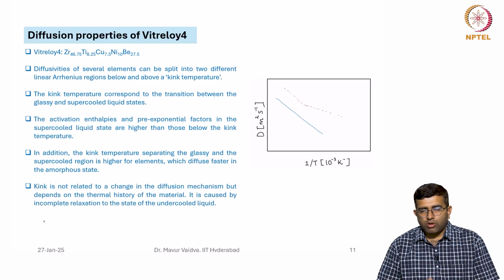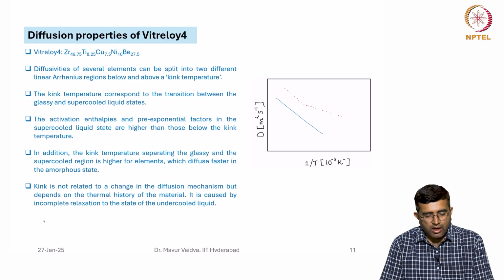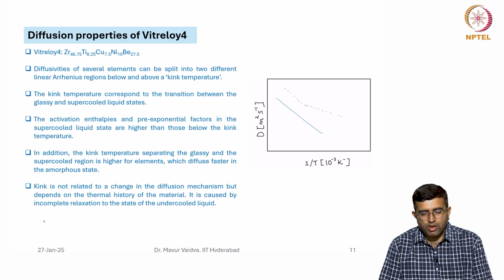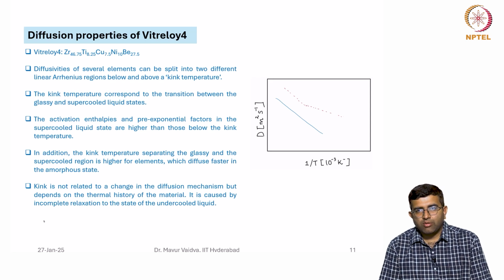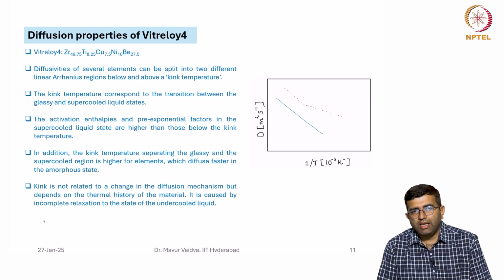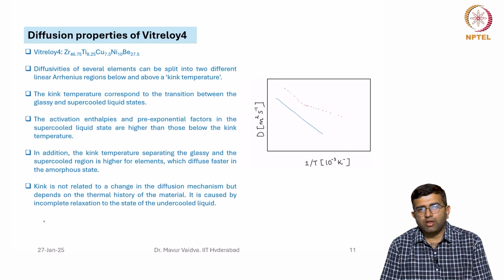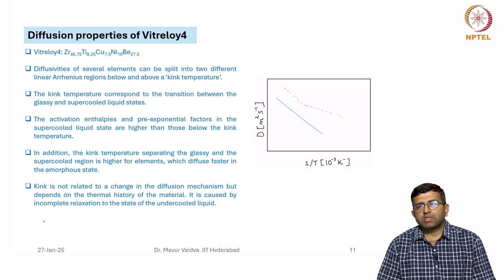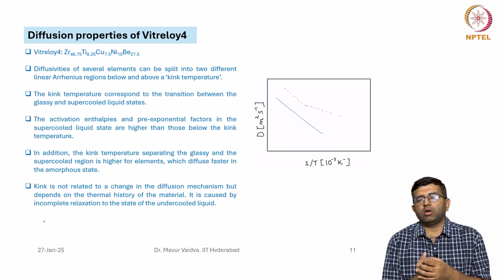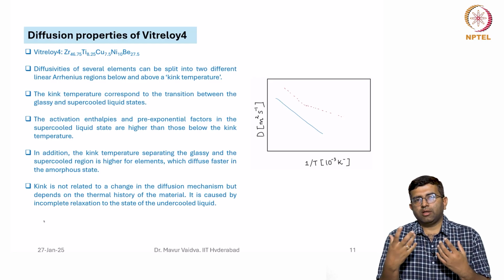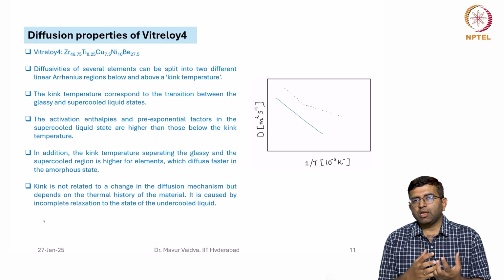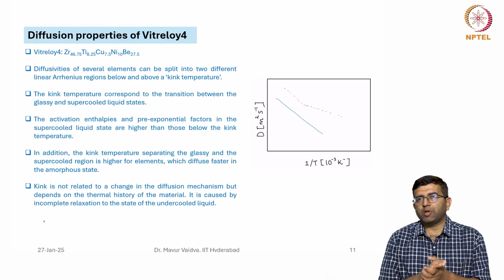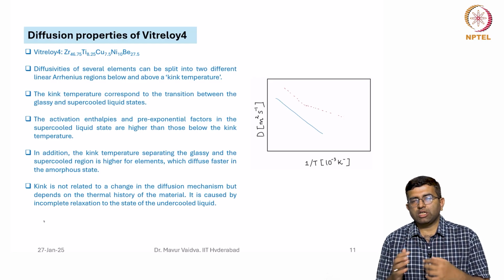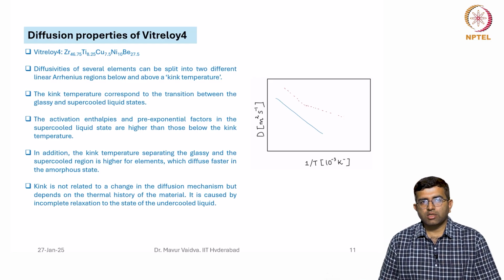What has also been observed in various research works is that the kink is not related to a change in the diffusion mechanism, but depends upon the thermal history of the material. It is basically caused by incomplete relaxation to the state of the undercooled liquid. That means when the glass is transforming to the supercooled liquid, the relaxation is not complete, and this is what causes a kink temperature, which leads to a change in the diffusion Arrhenius slope.